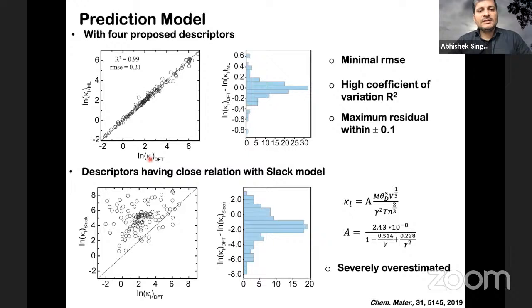And we compared it with a very popular Slack model, and you see how badly the Slack model performs. For almost everything, it overestimates the thermal conductivity. But if you look at the Slack model, this is the final formula for kappa L in the Slack model, you'll find that some of the variables or parameters which the Slack model uses are very similar to what we have found. For example, mass, volume, gamma. The only difference is their interrelation, which here was found through a highly sophisticated machine learning based algorithm. This was based on a semi-empirical approach.